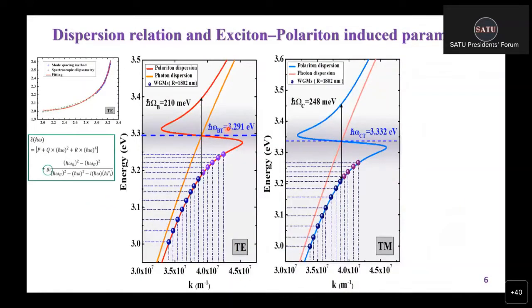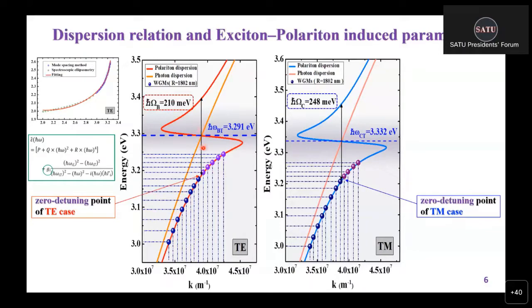So this is the E-k diagram, the energy dispersion diagram. We take TE as the example. The blue dashed line is the exciton energy state of the material. The orange line reflects the background dielectric constant. And the quasi-particles, the exciton polaritons, follow the new energy dispersion shown as the red line here. The observed optical modes are the solid spheres here. By the definition of the Rabi splitting energy, we can directly extract its magnitude, which is about 200 millielectron volts for zinc oxide.